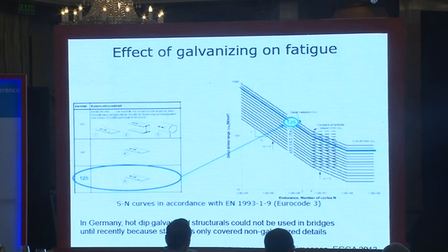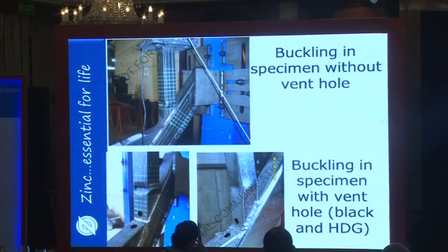What we found out was that the K-joints were not affected by galvanizing or by vent holes. You can see that the buckling always occurred away from the vent hole. The vent holes in their usual places do not influence the mechanical strength of these K-joints.